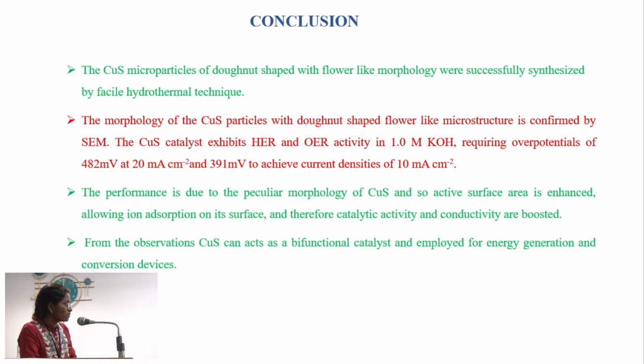The electrocatalytic activity has been enhanced due to the electrochemical active surface area of the material. Through this, I have confirmed that the copper sulfide with different morphology has enhanced electrochemical surface area and good catalytic activity for both HER and OER. I can confirm that it can be used as a bifunctional catalyst for the overall water electrolysis process. And the main thing, I have synthesized these materials without employing any surfactants or templates. So it is highly possible to scale up for industrial processes, and the overpotentials can be further reduced by adding some carbon compounds. Thank you.